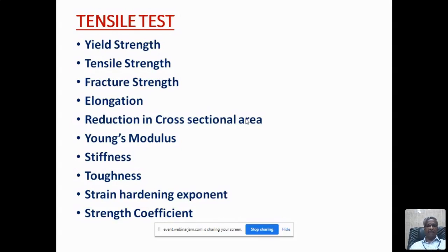So starting from yield strength, tensile strength, fracture strength, these three are related to strength alone. And then you have ductility parameters like percentage of elongation and reduction in cross-sectional area, and Young's modulus. Young's modulus, stiffness and toughness are also derived properties from the tensile test. And finally, as a further extension of this tensile test, you can determine the strain hardening exponent of the material and also the strength coefficient of the material. So these are the 10 properties. Maybe there are two more, making one dozen properties, characteristics or behaviors of the material, one can get by doing a simple test as per the standards and procedures prescribed by the standards. If you don't follow those standards, you will not get all the properties.